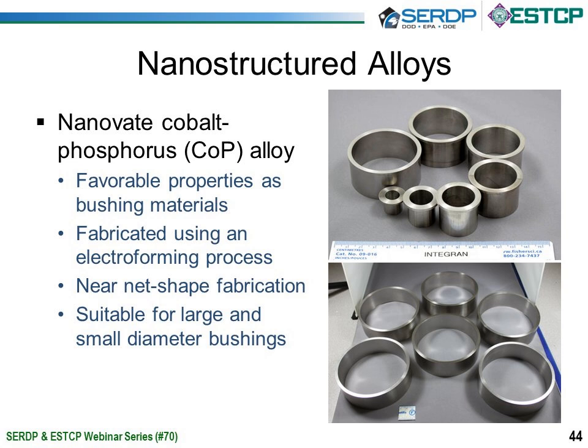In the case of bushings, the mandrel is obviously typically cylindrical with a smooth inner surface. The material that results is fully dense, needs no additional heat treatment, has a very smooth inner surface. And if the process goes well, the outer diameter is also relatively smooth, so bushings can be produced with minimal machining. Hence, we consider it a near net shape process. I suppose it might be considered an early additive process, or AM process, but it's not quite a fully additive process. As you can see from the images, it's a process that can be used for large and small diameter bushings.